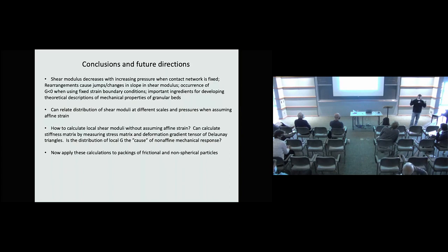So another way to describe it is that positive shear moduli, you're looking at the energy landscape, or the energy plus volume landscape, and those have positive curvature if you have a positive shear modulus. But I can explore states that have negative curvature because I'm holding the system there. Now, in nature, you can say, well, I believe in Newton, and so forces or stresses are important, and maybe that's not going to happen because they're going to run away to the next state. But I'm saying definitely in experiments, there are experiments done where I'm fixing the location of the boundaries, and those states with negative shear moduli will occur.